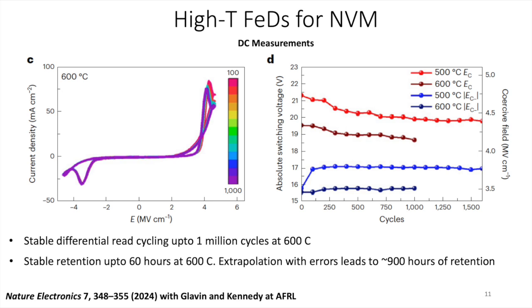Like most memory at elevated temperatures won't even have a write endurance of like 5 times. You try to write data into a memory element 4 or 5 times, it will fail at even temperatures of 200 or 300 degrees Celsius. Here we were able to write up to 1500 times at 600 degrees Celsius, again with no major issues. So we think if you multiply 900 times 1500, the total life cycle of memory that you can get in terms of time is huge. 900 hours multiplied by 1500, it's a very large number, right? So certainly for a mission on Venus, or a year-long or years-long mission in a continuously elevated environment, you shouldn't have a problem with this kind of memory.